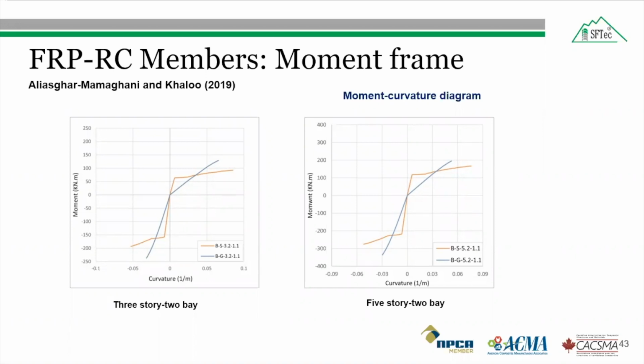The results from the study were the moment curvature curves at the plastic hinge region for beam sections of the 3-story 2-bay and 5-story 2-bay moment frames reinforced with GFRP and steel bars, which were compared. The GFRP bar reinforced section behaved linearly, however, and provided higher moment capacity than the section reinforced with steel bars. The ratio of the moment capacity of the beams reinforced with GFRP bars to that of those reinforced with steel bars was always more than 1, attaining a maximum value of 1.5 times the moment achieved by the steel members.